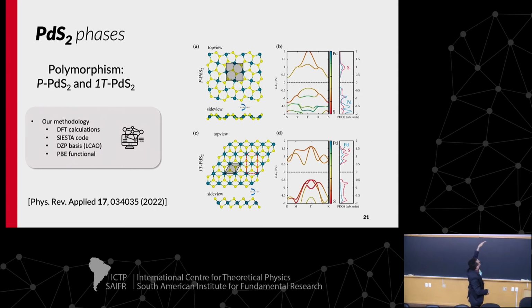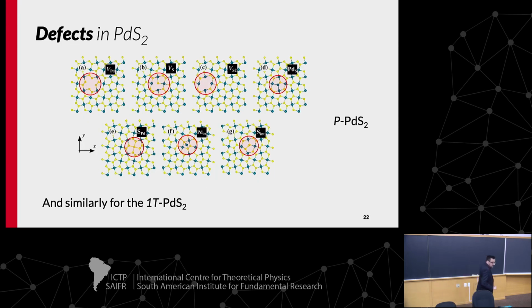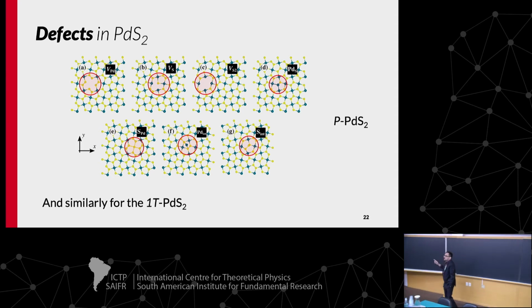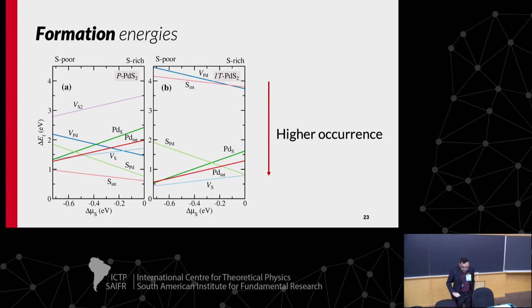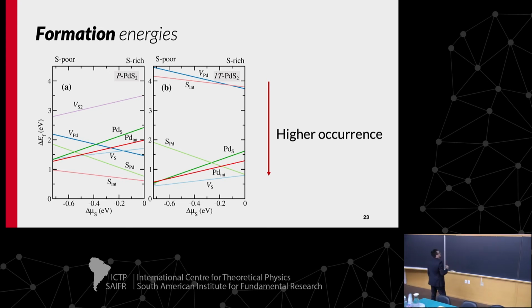In this case, we have two different semiconductors, and we did DFT calculations with these different phases, and studied the defects in this material too, like sulfur vacancy, palladium vacancy, divacancies, substitutional defects, and interstitial defects. And I'm showing here the defects for the pentagonal phase, but we have similar defects for the 1T phase. I'm not showing the 1T because it's very similar. But I'm showing the formation energy. We can calculate the formation energy for these defects in the PdS2.